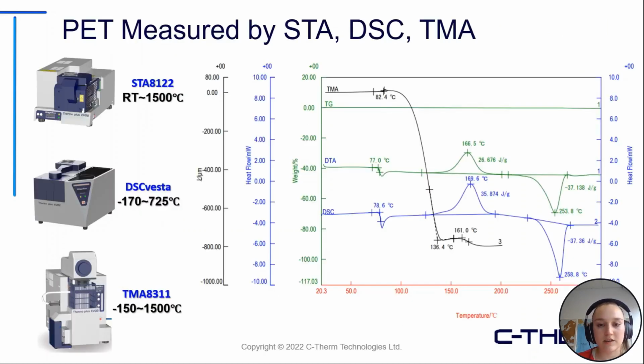Okay, so let's take a look here at a measurement of PET, actually done with all three instruments, so DSC, STA, and the TMA. In the TMA, it's actually the top curve. We can see a sudden increase correlating to the glass transition temperature at around 80 C. During the glass transition, the sample is soft and rubbery, and since the load is being applied to the sample, you can see a large shrinkage there.